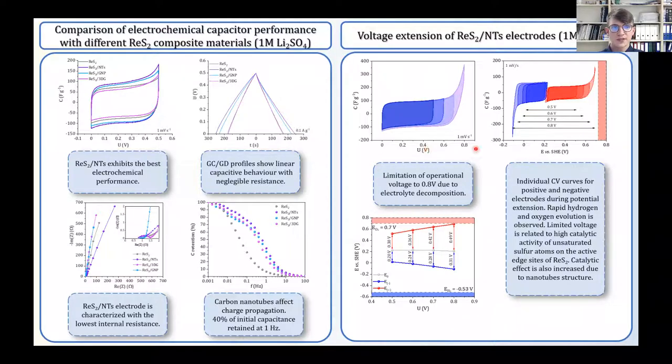Later we have decided to increase the operational voltage of this material, starting from 0.5V with the use of 1 mV per second. And it occurs that it was possible only to extend the operational voltage up to 0.8V.